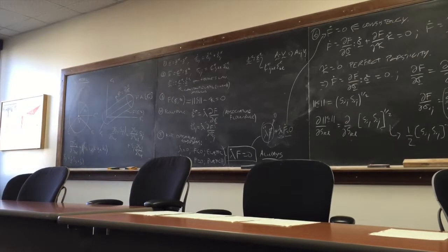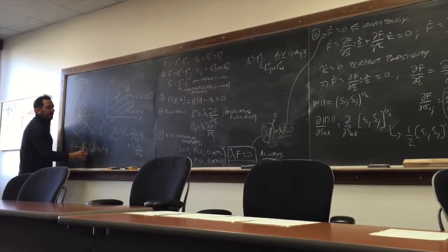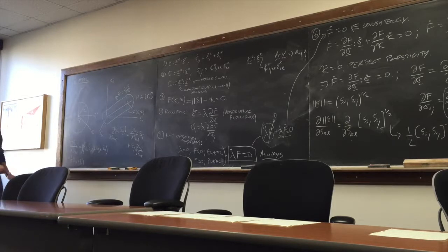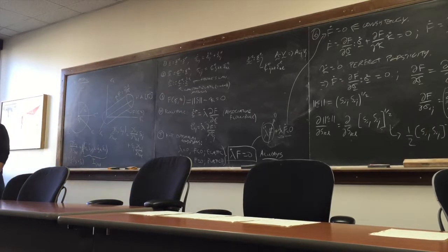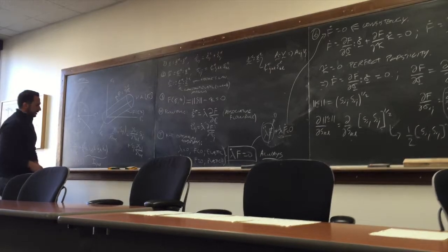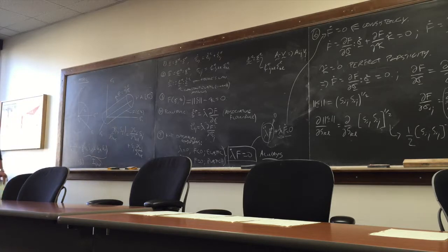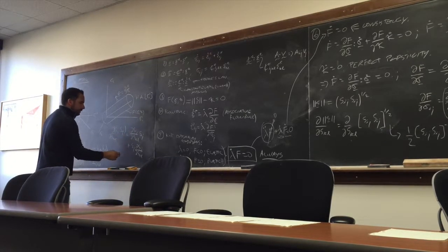then you get this formal result, and that will be important when you do the Voigt notation of all these things and you put it in a finite element code. If you just leave the formal correct part, which is delta ik, delta jl, you will lose this symmetry component, the symmetry property. So this is what people call the fourth-order symmetric identity tensor, because when you hit a tensor with that, you will get its symmetric part, not the full tensor, but just its symmetric part. See what I mean? So you gotta be a little careful with that. As long as everything is symmetric, there's no problem. But then once you start to put this in Voigt notation, this 1/2 will create issues for you if you're not careful.